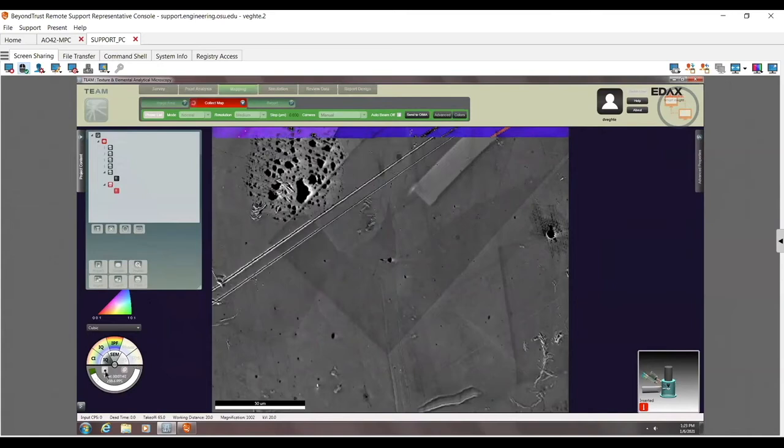Down here is what I call the smiley face. The smile here is going to be what we call CI through time. So right now we can see this is nice and green. Basically each one of these is like a little slice of row average CI. So we take the CI, average it for the row, and then basically make a color slice for this.